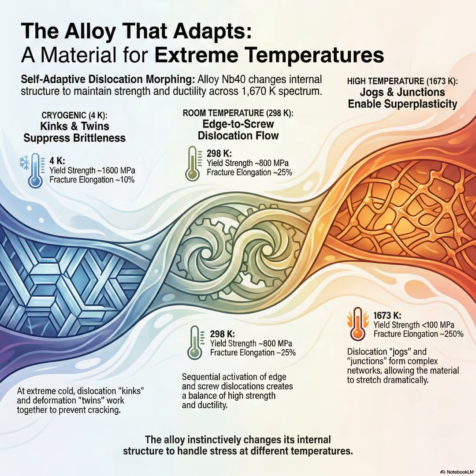So scientists started looking at these refractory high-entropy alloys. The refractory part means they have really high melting points, which is great for heat, but what was their Achilles heel? Ductility, especially when they got cold. They were fantastic at resisting melting, but they were still prone to that same brittle fracture at low temperatures. They had the strength, but no give.